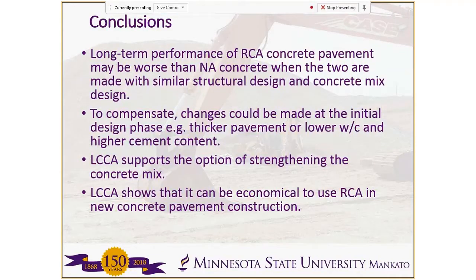So in conclusions, the long-term performance of the recycled concrete may be worse than the natural aggregate concrete if you just use a similar mix design and a similar structural design. To compensate for that, you can make some changes at the initial design phase. One option might be thicker pavements with RCA. Another option might be using a lower water cement ratio and a higher cement content.